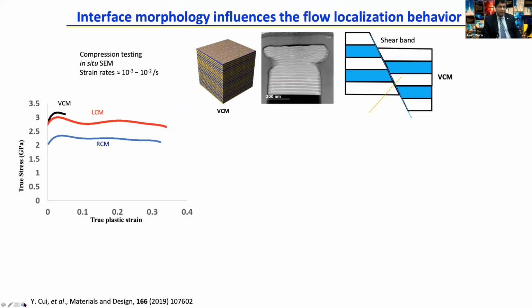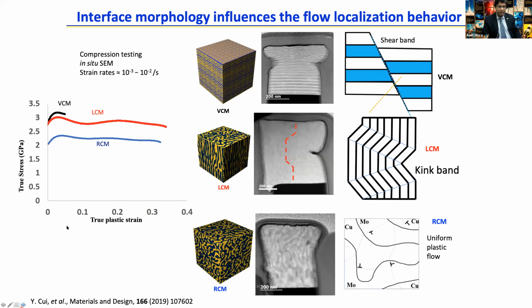And we see a very significant effect on compressive properties. This is all compression. I will show other tests later. On the morphology, for nominally the same length scales, it's not possible to have exactly the same, but for nominally the same length scales, you see different morphologies have very different stress-strain response and very different deformation modes. So the one at the top, the vertical concentration modulation, or the multilayer structure, is what I showed before, the in situ deformation. Very high strength, but at the point of yield, it just fails by shear localization. Because once you start pushing dislocations across and cutting across the interface, you localize a shear band. So it is very hard, but does not propagate plasticity across.